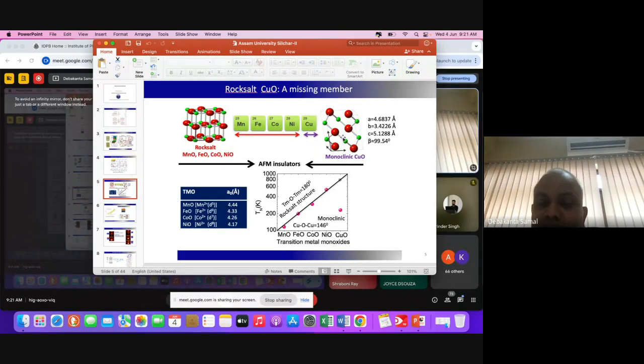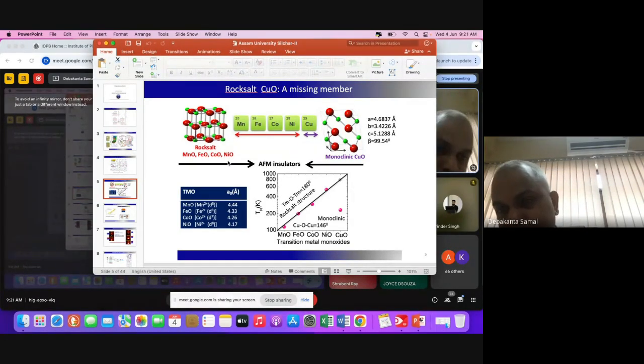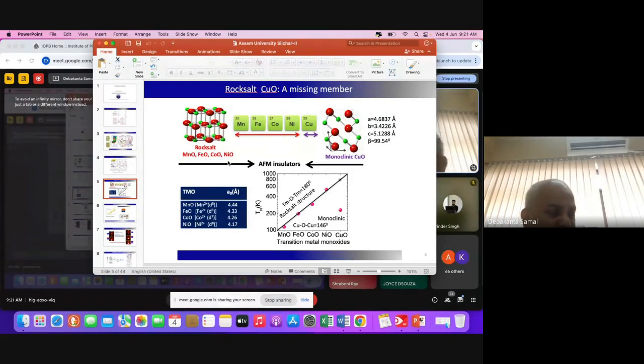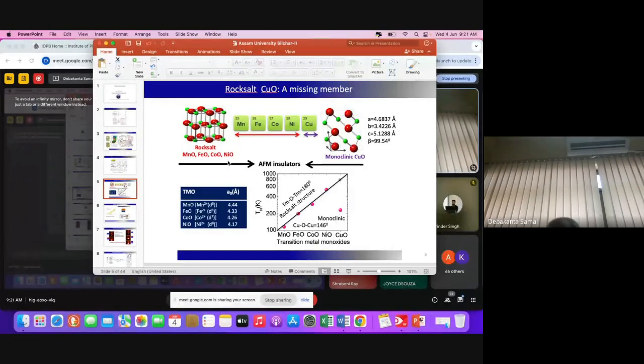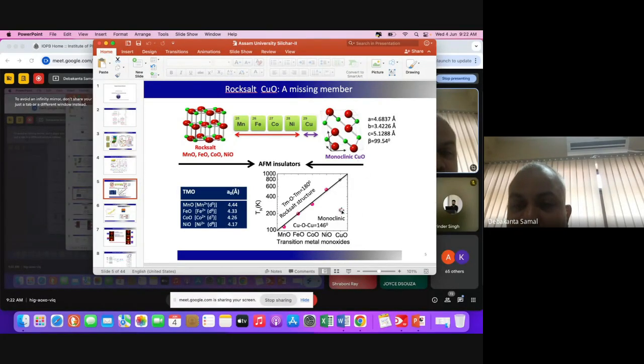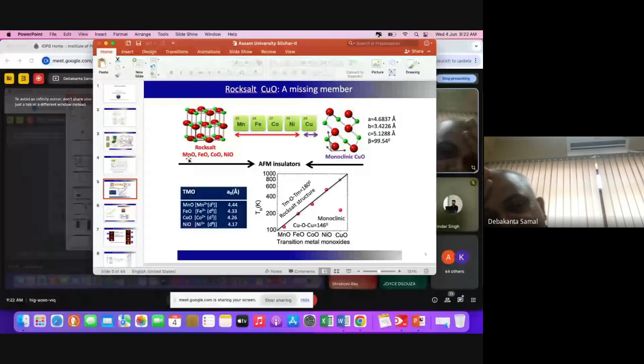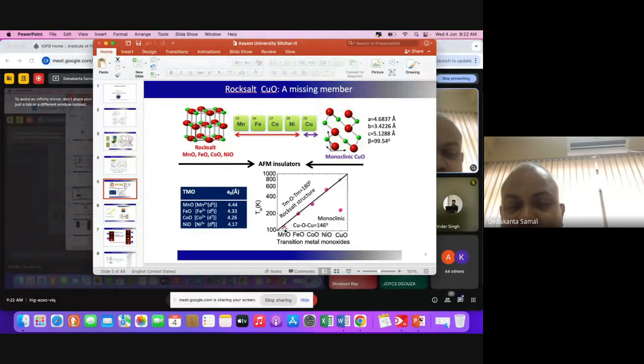If you look at the Néel temperature, these are all antiferromagnets. Manganese oxide, iron oxide, cobalt oxide, nickel oxide are all antiferromagnets. Their Néel temperature: manganese oxide is roughly more than 100, iron oxide is a little close to 200, cobalt oxide is less than 400, like this. But when you come to copper oxide, you see a linear trend increasing as you go from manganese, then iron, then cobalt, then nickel, then comes copper. So one should expect that if it is just increasing with the periodic table elements, then one should get a point like this, the blue point, for copper oxide.